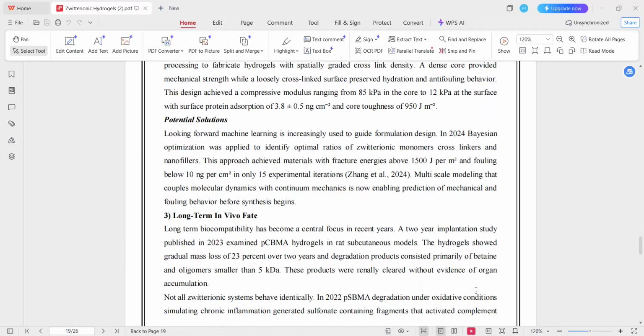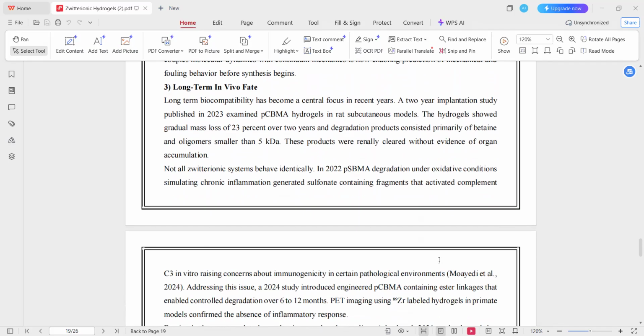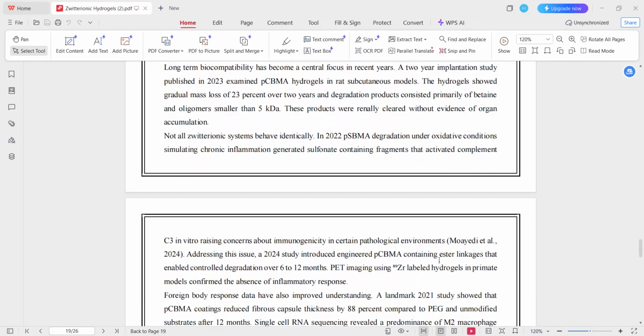Long-term in vivo fate. Long-term biocompatibility and degradation behavior represent another critical challenge. A two-year implantation study published in 2023 examined carboxybetaine methacrylate hydrogels in rat models. These hydrogels showed a gradual mass loss of 23% over 2 years, with degradation products consisting mainly of betaine and small oligomers that were safely cleared through the kidneys. However, not all zwitterionic systems behave identically.